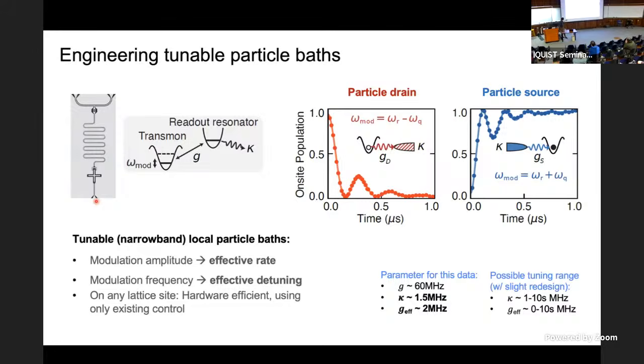So you can see, okay, so these are the resonant conditions, right? Which corresponds, for example, in this case, a particle resonantly leaking out to this effective bath with line width kappa and some effective coupling. So if I change this modulation frequency, you can essentially think of this bath being moved up or down in detuning in frequency, right? And the strength of the modulation is what changes this effective coupling, because it's how strong the sidebands are, how much population of the qubit is put into that. Yes, correct, exactly, yes.